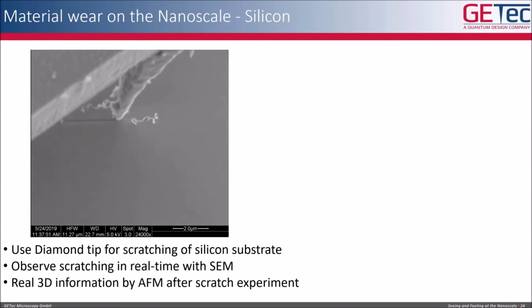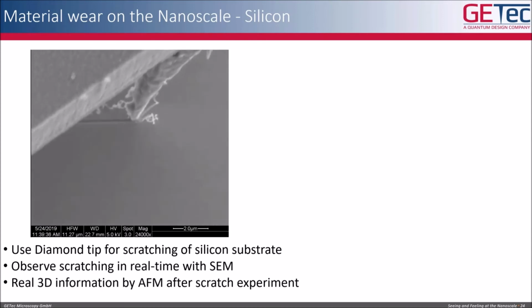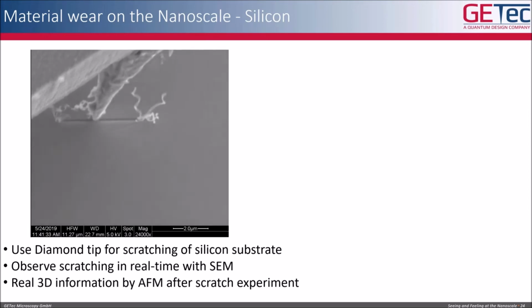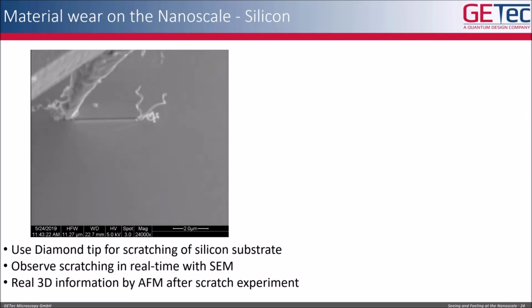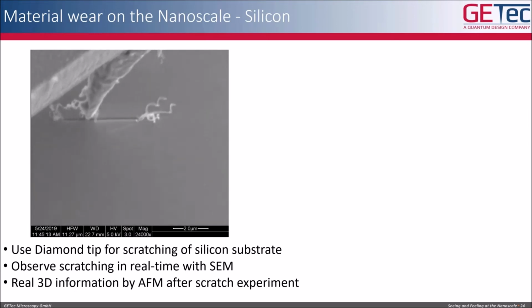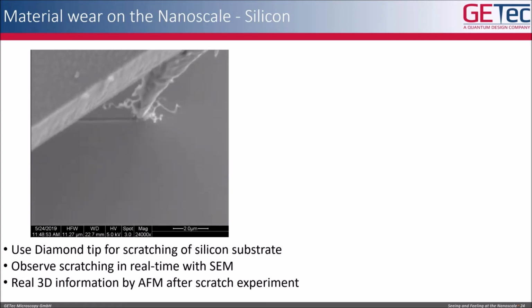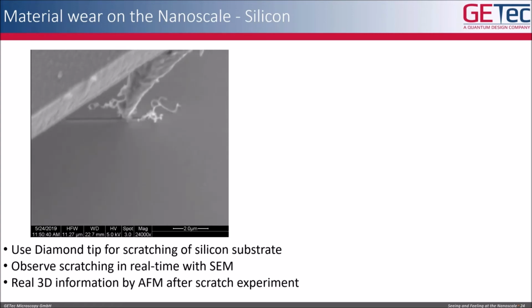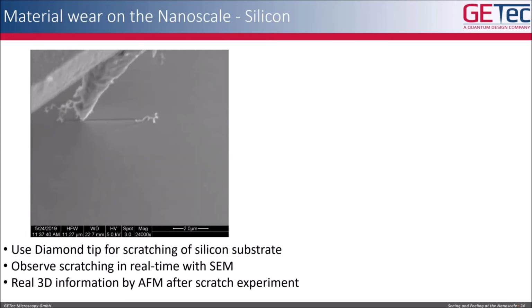And I like this video very much because it shows you not only that we can really observe with the SEM what you're doing with the AFM, but it also shows you how wear resistant these diamond tips are. So you can really scratch away the silicon surface without harming the tip.